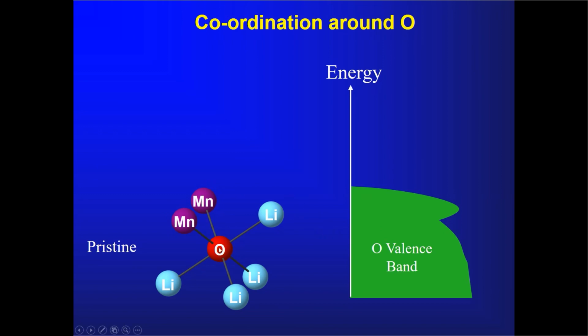So what we're going to focus on is the oxygen 2p levels, because those are the things which we're oxidizing, we're removing electrons from, and we're putting them back into. So this is the coordination around an oxygen in our pristine lithium transition metal oxide. The oxygen sits here between the alkali metal layers represented by the lithiums here, and the transition metal layers represented here. And as I said, in a stoichiometric material that doesn't have oxygen redox, all three would be transition metal ions. The difference in a lithium-rich or oxygen redox material is you now have lithium in the transition metal as well as the alkali metal layers.